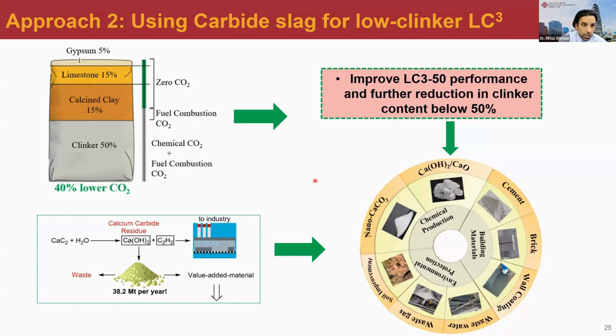The problem is that when we want to further reduce the cement, the reactivity of this calcined clay cannot be fully utilized, because there is not sufficient calcium hydroxide. So we tried to find some industrial waste which can supply calcium hydroxide. In this case, you can see that we found carbide slag, which is a perfect candidate.